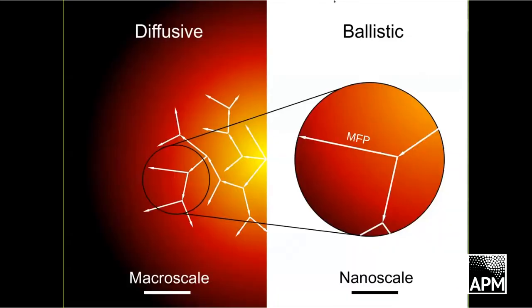When we talk about heat conduction, usually we imagine a diffusive process on the macroscale. However, as each phonon can be represented as a particle of lattice vibration, it has a mean free path, which is usually estimated in silicon at room temperature as about 10 to hundreds of nanometers, which means that at the nanoscale, we should feel the phonons actually moving as particles, so-called ballistically. And if we probe heat conduction in nanostructures of this small scale, we should be able to feel almost no resistance, or at least reduced resistance as compared to bulk conduction.